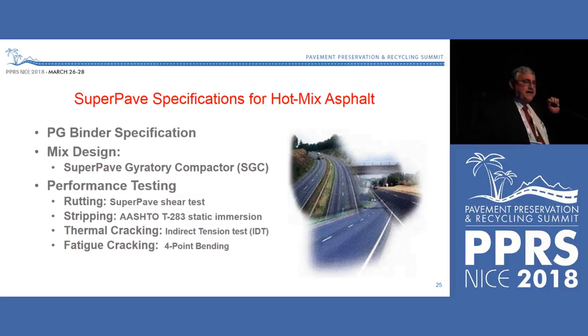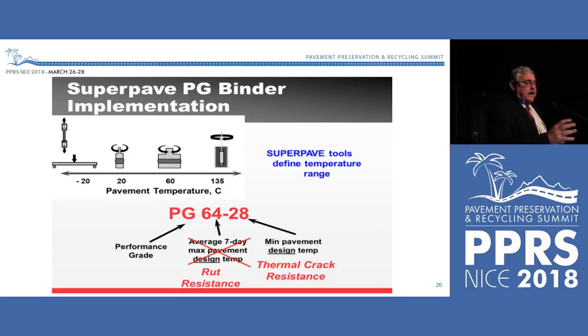But the important thing is the failure criteria, what we're after in performance is what's important. If you define the failure criteria for an application, then you can choose and adapt the test methods to fit as best you can with the failure criteria you're trying to match. For example, in the binder specification from the hot side, we've got the Brookfield for mix and compaction temperatures, a dynamic shear rheometer test at high temperatures to define rutting that's now changing from the original G*/sin delta to a multi-stress creep recovery test. So the tests are changing, but the tool's the same.